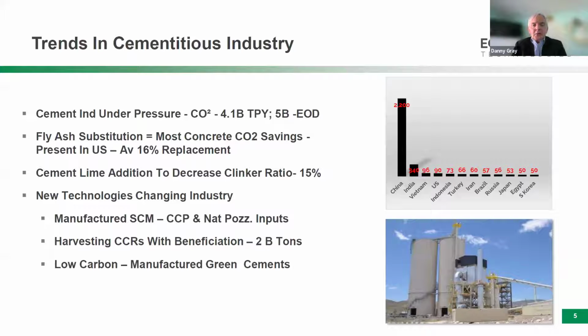If you look at it on a worldwide basis, USGS estimated that 4.1 billion tons of cement are produced. That's metric tons. And we're going to have 5 billion tons produced by the end of this decade. And you can see from a country origin where the production is coming from. China obviously dominates the cement production on a worldwide basis, and you can see that in the graphic. Fly ash substitution: fly ash is in most concrete and is used to reduce the CO2 footprint of the embodied concrete. In the U.S., we have roughly about a 16% replacement of fly ash today.